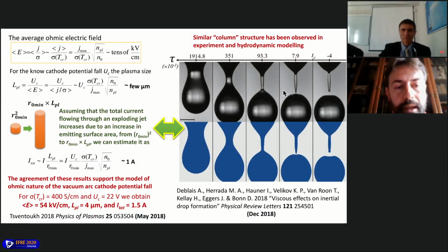Also, we can estimate from this model other specific things, like average ohmic electric field. So we have current transfer through the media, and we have some ohmic electric field that arises due to this and provides this current transfer. This estimation is shown here. It shows about tens of kilovolts per centimeter. It is an electric field that can provide the current transfer.